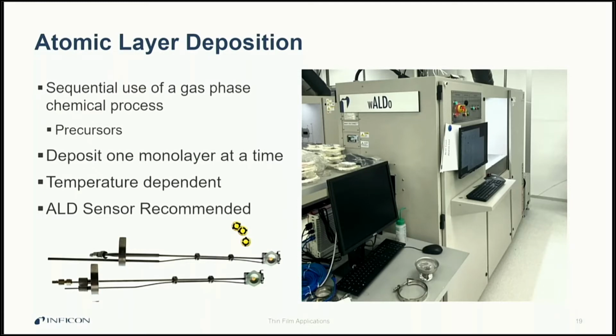Atomic layer deposition, or ALD, is a type of CVD application with some key differences as to how the reaction takes place. For CVD, all precursors and reactants are added to the chamber at once, while ALD goes through a sequence of precursors in order to deposit the desired film. The sequence is usually a 1-2-1-2 style deposition, but the sequence is often larger than 2 cycles. ALD systems are used to deposit one monolayer at a time in a very controlled deposition. However, chemical reactions are very temperature dependent, and the substrate must be kept at a set temperature for the deposition to take place.